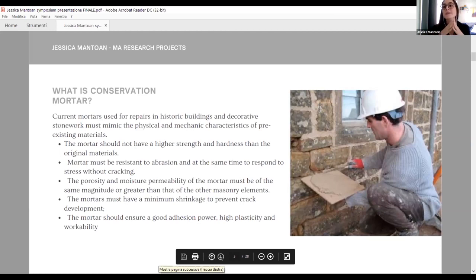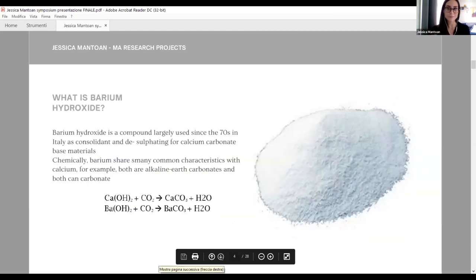That means that it must be easy to use, present good adhesion power, and high plasticity in order to achieve the best result possible. The other character of my research is the barium hydroxide, the additive that I use to prepare my mortars. Barium hydroxide is an inorganic chemical compound, the hydrated form of barium oxide, and in Italy it was largely used during the 70s as a consolidator for limestone and in particular wall paintings, due to the high reactivity with limestone substrate and in general carbonate substrate.